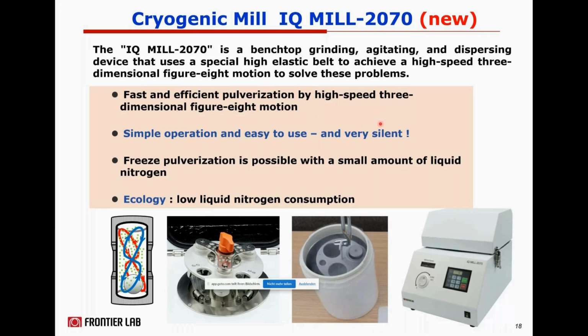It pulverizes quite fast and efficiently by this high-speed three-dimensional figure-8 motion, and you see that here. This is a schematic drawing of the milling vessel. Inside we have crushing balls, which can be made from stainless steel, tungsten carbide, or zirconia. You put the milling vessel in here and fix it, so the operation is very easy. Also, and this is a big highlight, it is a very silent instrument. You don't need ear protection, or a separate room for it.